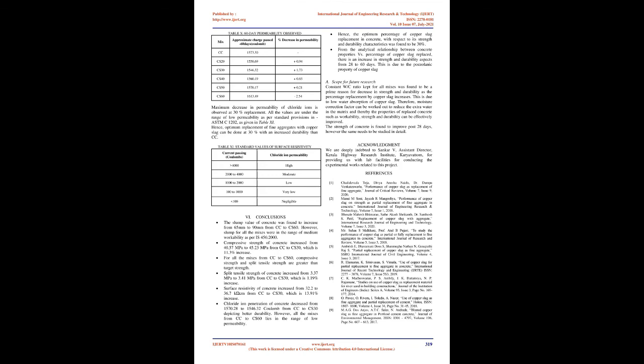Hence, the optimum percentage of copper slag replacement in concrete, with respect to its strength and durability characteristics, was found to be 30%. From the analytical relationship between concrete properties and percentage of copper slag replaced, there is an increase in strength and durability aspects from 28 to 60 days. This is due to the pozzolanic property of copper slag.